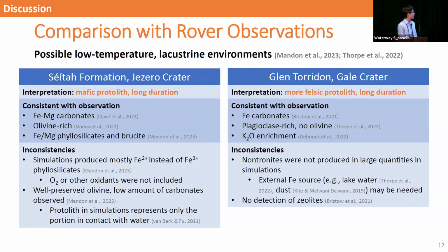And this may be explained by the lack of oxidants in our simulations. Also, Séitah Formation contains well-preserved olivine, and the amount of carbonates is low compared to the complete dissolution of our protolith in our simulation. And this can be explained by the protoliths in our simulations representing only the parts that actually interacted with water instead of the whole rock.